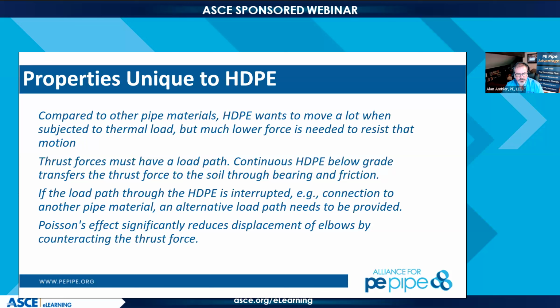Okay, so we got a couple of great questions, and I'm going to get two of them live here real quick. We had one question about thermal effects for HDPE as installed through open cut construction. So the earth, once we've dug through and installed the pipe through the earth and we have a stable environment in the ground, there typically will not be any substantial temperature change unless the fluid conveyed through that pipeline changes significantly. The two primary areas as to which we worry about thermal constraints is a temporary condition for moving the pipe above ground when it could be hot to below ground while it's being installed until that's stabilized. And the other is changes in the fluid as it's conveyed through there.